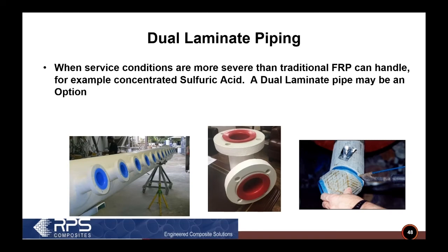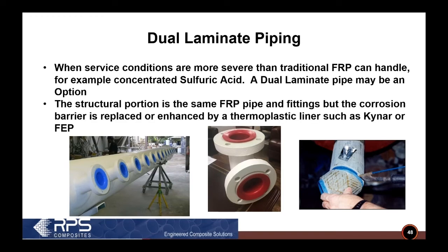So you have the properties of an FRP pipe. So you think about when we use HDPE, for example, you have the properties of FRP pipe, not HDPE pipe, but you have the chemical resistance that you need. So for example, the chemical resistance of Kynar, and that's why you can use sulfuric acid. The Kynar will resist that, or the FEP, but you have the corrosion resistance and the strength and lightweight characteristics of the FRP. And this just says in the next slide that the corrosion barrier is the thermoplastic, and the rest of the pipe is just the same FRP pipe as your straight FRP pipe that we've been talking about all along.